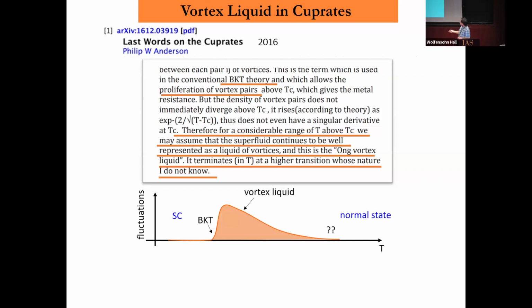So the fluctuation signal, or the vortex signal, as a function of temperature in cuprates, he's trying to describe like this: in the superconducting state you don't have the signal, and then you have a KT type of transition allowing a proliferation of vortex and anti-vortex. There's a wide range of temperature where you have this liquid state of vortex, so they are mobile. That's why you lose the resistance.